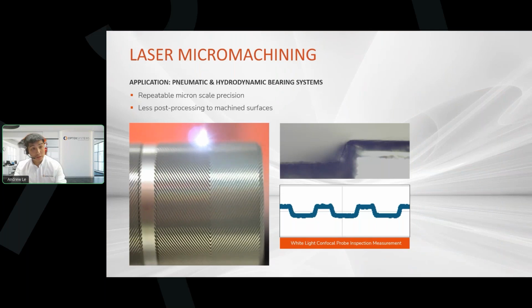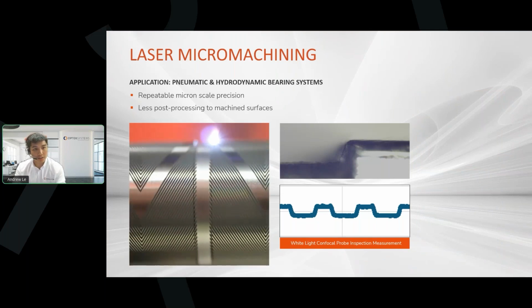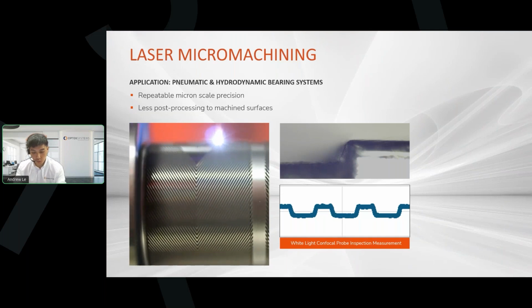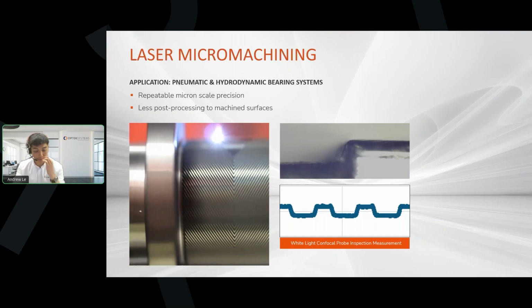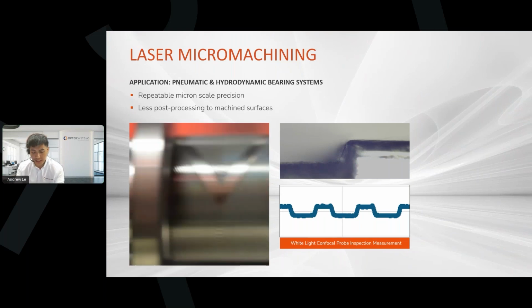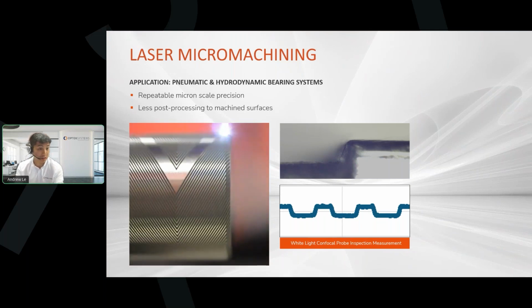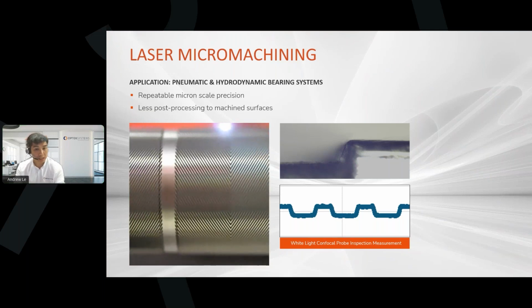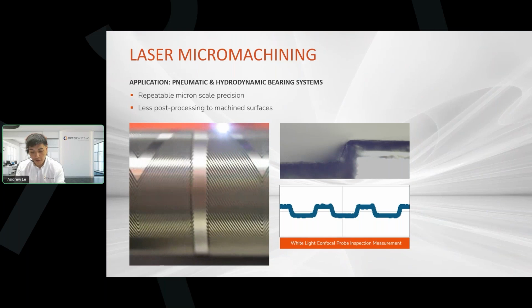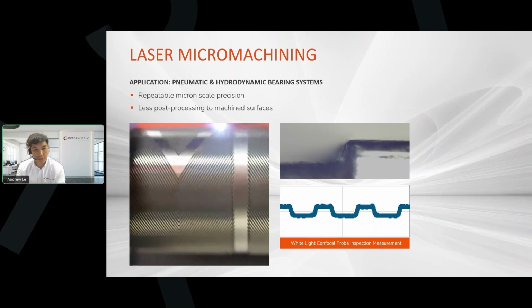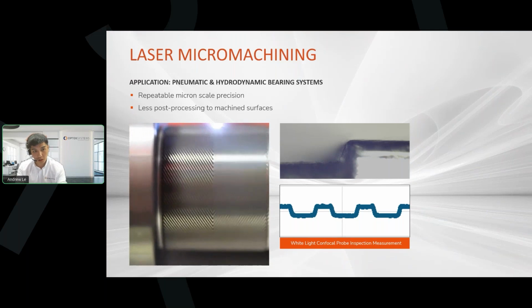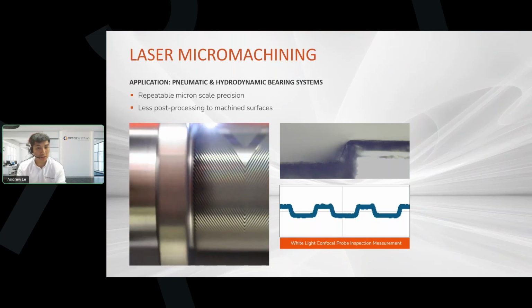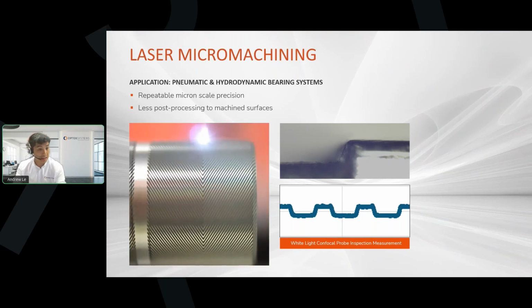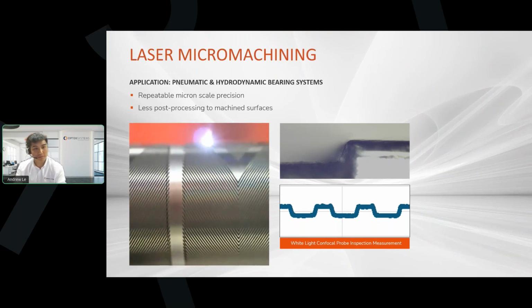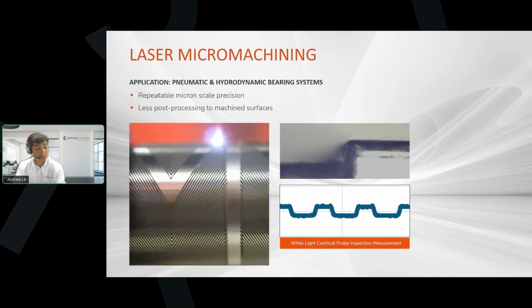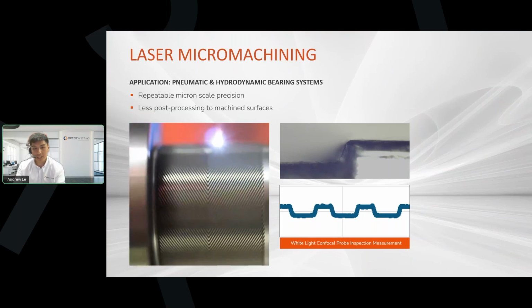For our first example of a real-world application of laser micromachining for hardened materials, we're looking right here at a gas pneumatic bearing or hydrodynamic bearing. These systems are usually made up, in this case, of shafts of molybdenum, but they're also made up of titanium and case-hardened steel. Often, these systems require very specific machining with very low tolerance requirements for the patterns and groovings. What this means is that they have to be repeatedly produced, and we have to make sure that we're doing it as consistently and verifiably as possible.